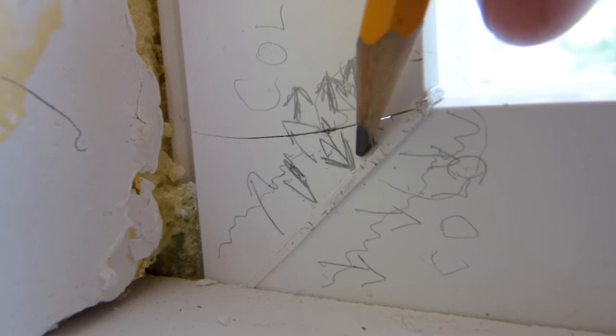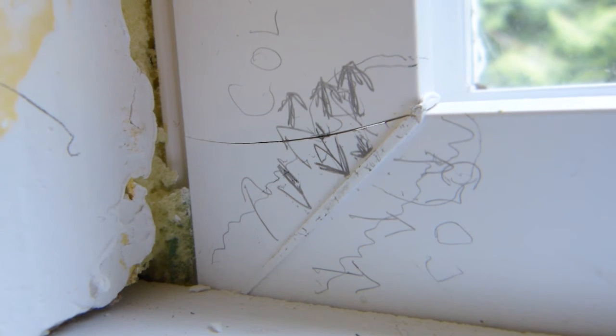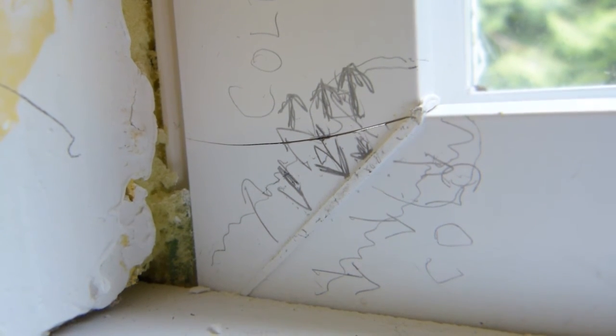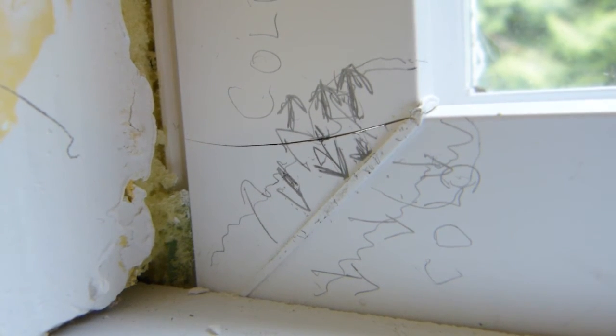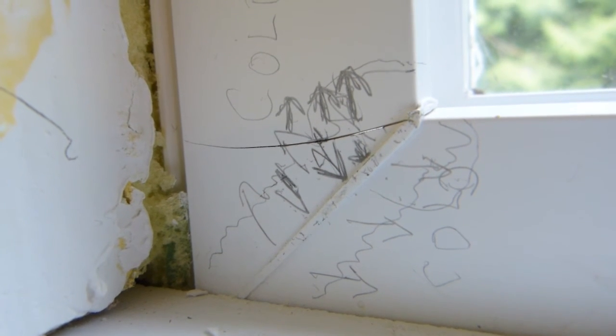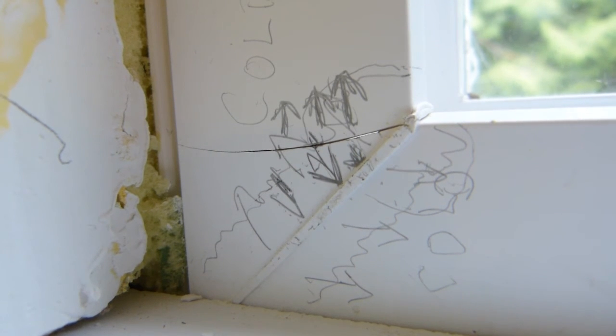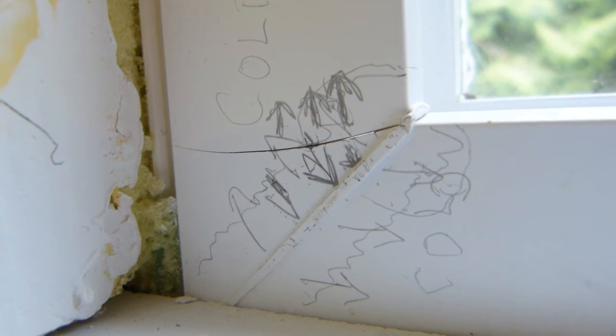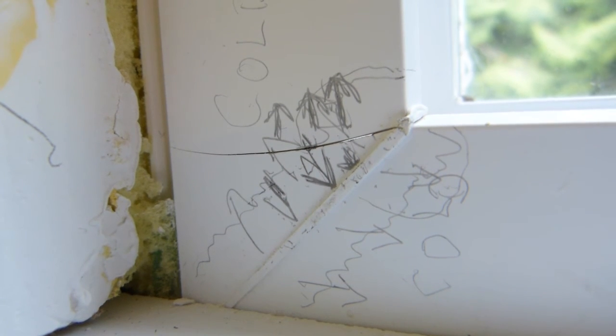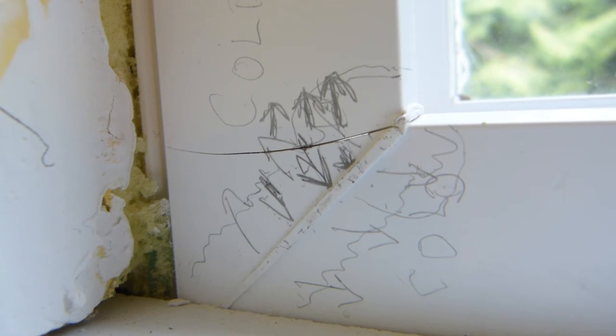So the forces are greatest here, pulling the heat affected and the not heat affected zones apart here, and less so here and here. So that's why it cracks days after manufacturing, days after quality control at the manufacturer's site. It cannot be caught at the manufacturer's site because the crack is not visible at that point. The internal stresses are there, but the material tears itself apart a little later, much like honey, liquid at first, solidifies and crystallizes later. When it's liquid and it's hot, it looks good. When it solidifies, it looks good. A month later, maybe it still looks good, but eventually the internal stresses cause it to crack.